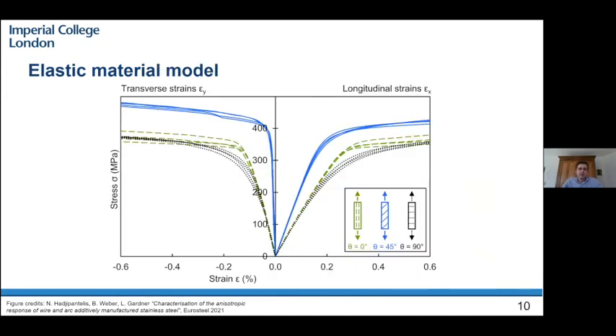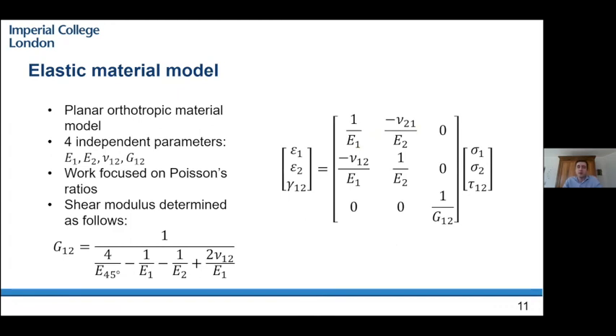Looking at the stress strain graphs of the same coupon tests, this anisotropic behavior manifests itself again, where the three different directions behave vastly different from each other. So we can't really utilize a normal isotropic material model that would be the initial assumption for steel structures. So upon research, we came up with a planar orthotropic material model that fits our material behavior best. Essentially a planar model because our structures are relatively thin compared to their longitudinal and lateral directions. So we were able to use shell elements in simulation.